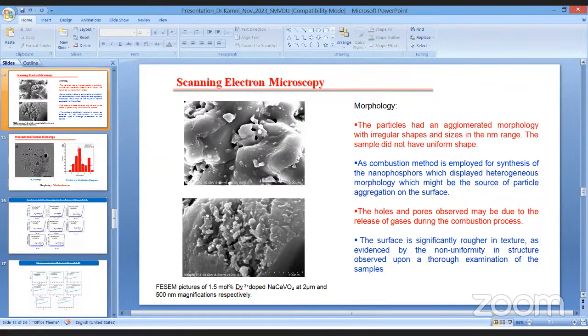Some pictures were used to examine the surface morphology, and this method is frequently employed in the characterization of nanomaterials. So as you can see, the particles had an agglomerated morphology with irregular shapes and sizes in the nanometer range. The sample did not have a uniform shape, and we know that as combustion is a very fast method employed for the synthesis of nanophosphors, it displayed heterogeneous morphology, which might be the source of particle aggregation on the surface.